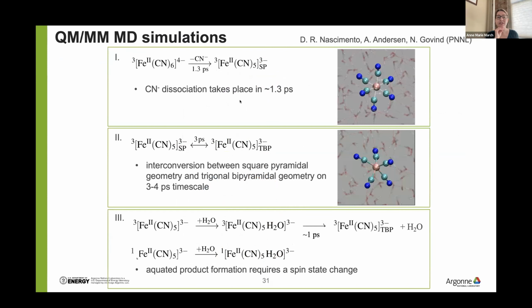And then Neri and Amity did some quantum mechanical molecular dynamics simulations to try to understand what's happening here. So they start out with this first one here. They start out with the ferrocyanide in a triplet state, so that excited triplet state. And they find that it releases the CN, and it takes about 1.3 picoseconds for the CN to kind of fully make its way away from the complex. And this leaves it in this square pyramidal geometry.